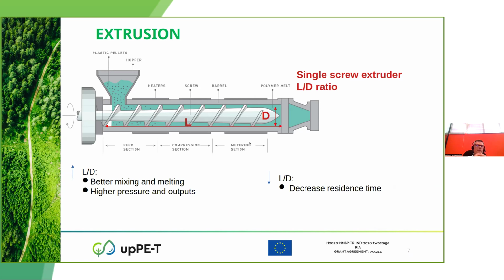Regarding the mixing and melting, a higher L/D ratio generally provides better mixing and melting of the polymer. This is because the material spends more time within the extruder, allowing for more thorough heat transfer and shearing. Conversely, a lower L/D ratio may result in less uniform melting and mixing. Regarding the output and pressure, the L/D ratio can also influence the output rate and the pressure generated within the extruder.